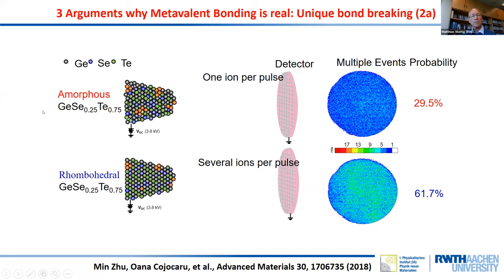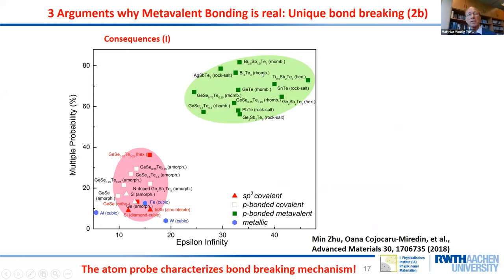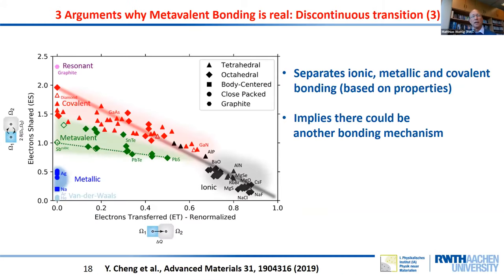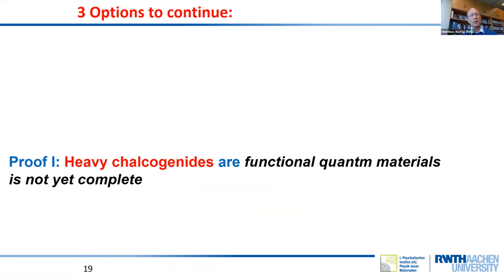And now we can compare this in this graph here, and you can see that all of these materials in the green region show this atypical bond breaking, where we have a high number of multiple events, while this is not the case for metallic or covalent systems. So this is another reason why this seems to be a unique bond. And finally, we have been traveling the border here from metavalent to covalent behavior, and there always are discontinuous property changes. So this is a very well-defined border between green and red. So this is convincing us that scientifically, this is a good map with predictive power.